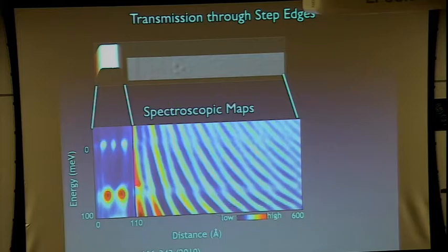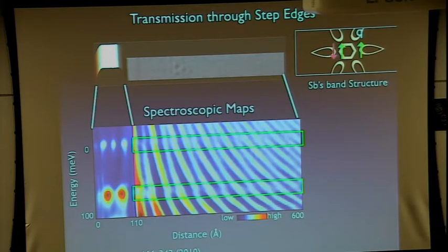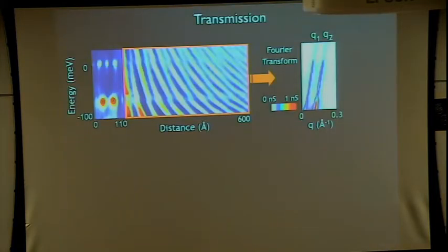So these waves are basically dispersing. And what you notice is, out here, just as you hit this resonance, there is a change in the reflectivity of the waves. So this is just like your Fabry-Perot interferometer. It's very simple. And you can take this data and Fourier transform it. And you can see that there are suppressions at specific values of energy.